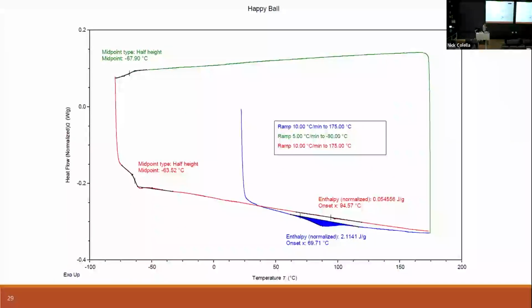So this is a typical DSC curve. This is for the happy ball. So we start at room temperature, and we're going to heat, and then we'll get a melting peak around 75. Onset is 69, and then we cool back down. We don't see any transitions until we get down to -70, and we see this is a glass transition, and we heat back up and we see the glass transition again.